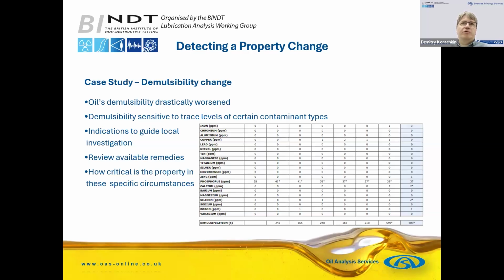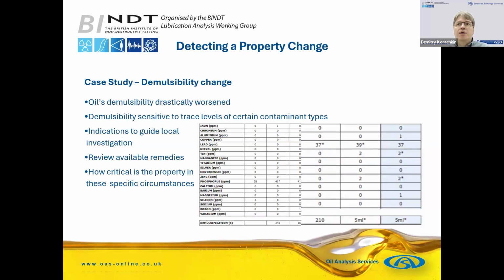But it's not just about finding out what the contamination is, it's also finding out what you can do to deal with it. And in this situation, whether this property is critical or not, because demulsibility is important when there is water getting in, but if you have very good controls of moisture levels, no water getting in, you may be able to continue with this condition where demulsibility is not ideal. So we saw, as I said, a little bit of calcium and a little bit of silicon, which initially did not strike us as particularly high and abnormal, but once the problem was confirmed, we investigated further, and that was a possible cause for the demulsibility problems.